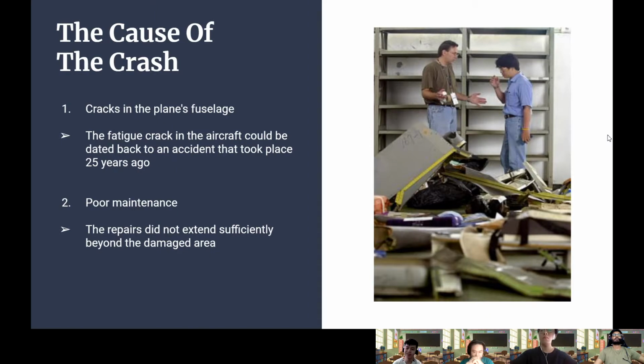On February 7, 1980, the aircraft suffered damage when its tail touched the ground while landing in Hong Kong. Although the damaged plane was shipped back to Taiwan and underwent temporary repairs the day after the incident, permanent repairs conducted by the nation's largest carrier, China Airlines, were flawed. China Airlines did not repair the damage in accordance with Boeing's structural repair manual. The damaged skin should have been either trimmed or removed as the standard procedure required, but the repairs did not extend sufficiently beyond the damaged area and thus did not restore structural strength.